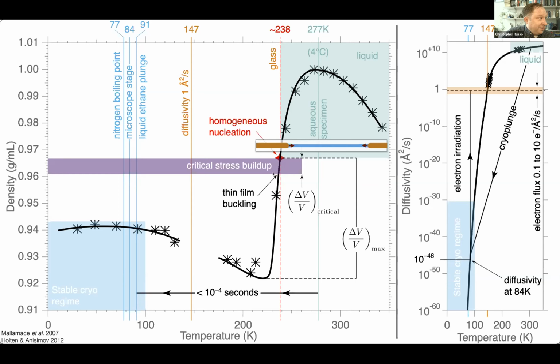So the buckling event actually happens not while you're imaging it in the microscope. It happens while you're making the grid, while you're actually plunging the grid. And then the stress that builds up after the buckling event releases it is then the difference between the density here and the density that you finally end up at when you go all the way down to 100 Kelvin or so.